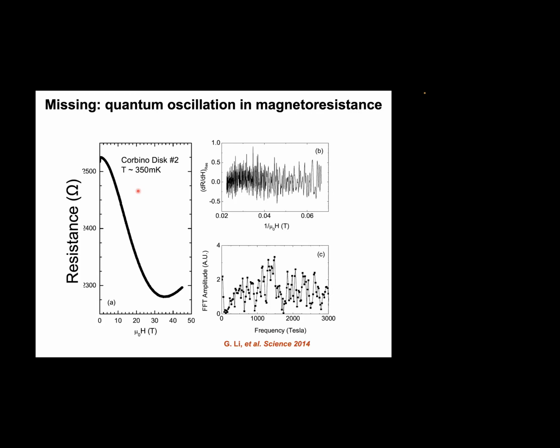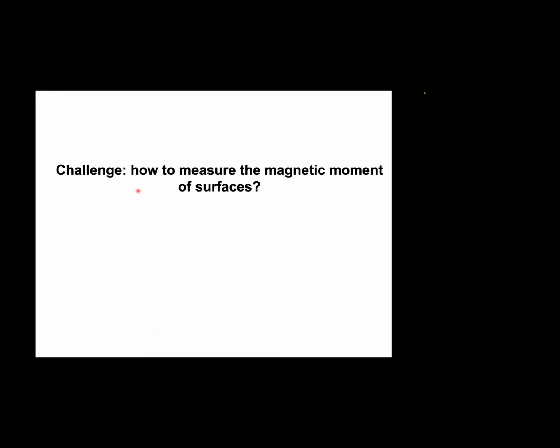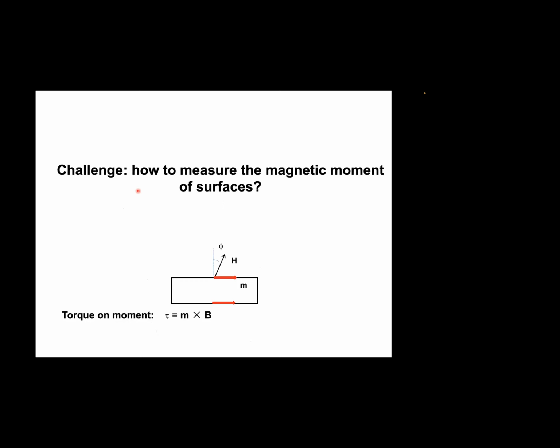But we knew that the fundamental quantum oscillation should come from thermodynamics or magnetization, which is directly proportional to the density of states, or proportional to the change of free energy. Because from Jackson, we know that magnetization is nothing but dF/dB, right? So the question, of course, is that at that time we thought it's coming from surface states, and the immediate question is how would we measure the teeny tiny volume of surface? So we decided to measure magnetic torque, just like how we align a compass. We have a field, any dipole moments would try to follow the magnetic field direction, and that's a result of magnetic torque, M cross B, right?